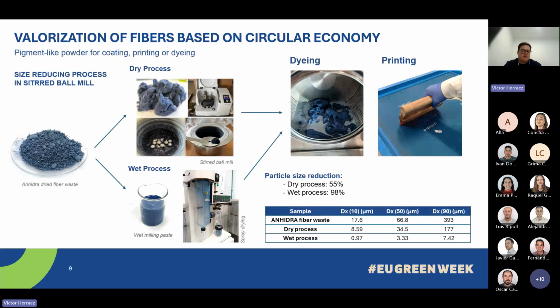So for the size reducing process, we've taken the dried fiber waste we obtained from the ANHIDRA system. Then we have two options: just put it in a stirred mill, and we get a 55% particle size reduction, or we've tested a wet process where we put the fiber in a water suspension, then stirred mill it, and then we get a slurry that we can spray dry, and then we get a powder with a 98% smaller size distribution. Then it's similar to conventional pigments, so we can apply it as in traditional dyeing or printing routes.